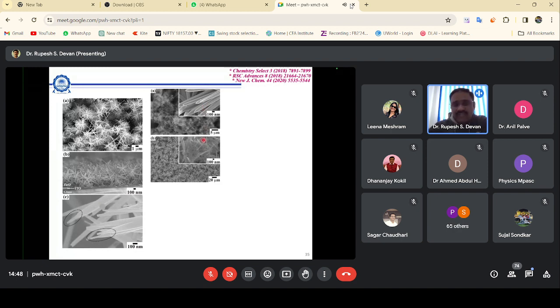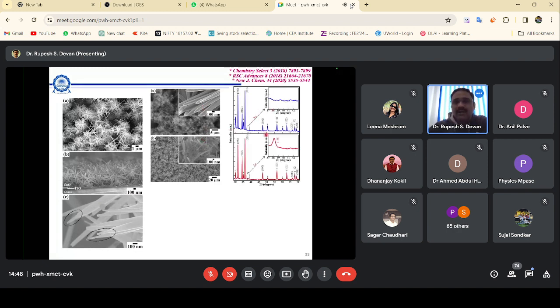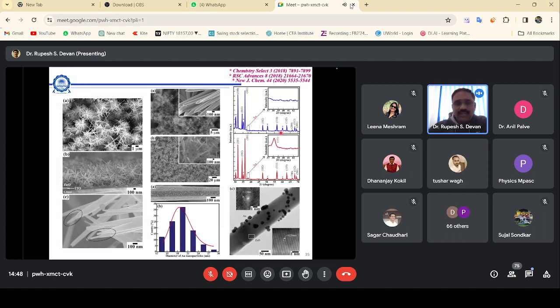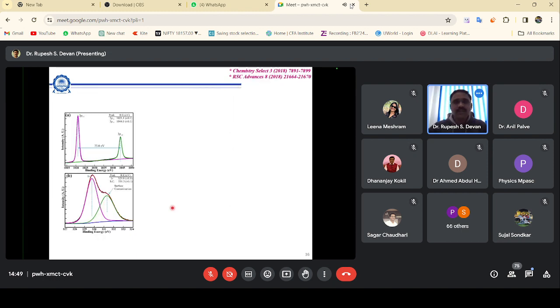And then this gold content has been varied. You can see here with pure zinc oxide there is no gold, and when you decorate with gold, you can find a gold signal. You can even see that these gold particles are nicely decorated over this 1D structure, and the particle size is close to 20 nanometer. Most of the particles range between 18 and 21 nanometer. Now, what is being done here? The gold concentration has been varied to decorate this structure layer by layer.